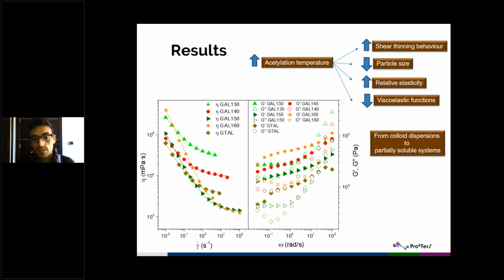So what's the comparison between commercial lubricating greases and this system that we have obtained? In fact, these rheological results, both the viscoelastic function and the viscous values, highlight that this system can replace those commercial lubricating greases from low NLGI grade.